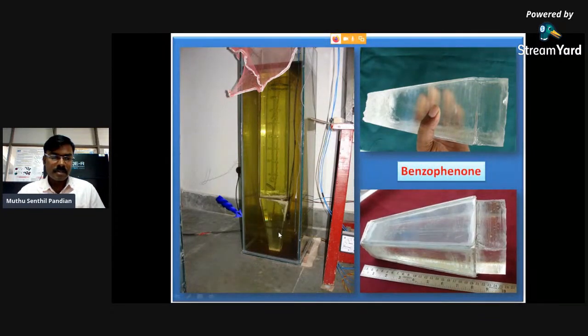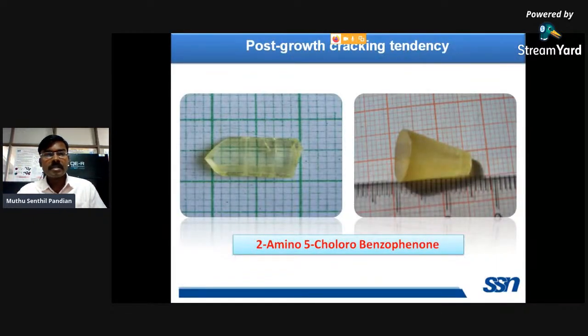So this is the organic benzophenone single crystals for nonlinear optical application. We can grow square shaped, rectangular shaped, and prism shaped crystals. You have to select the ampoule shape, then any shape is possible in this SR method. Crystals which have a post-growth cracking tendency can be avoided in the SR method.